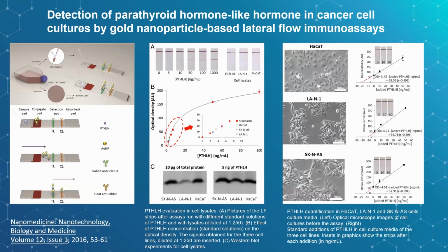And we offer these devices based on gold nanoparticles and with special receptors for the detection of this hormone. The idea was to use this device for testing some drugs that colleagues were developing, and we wanted to have a very simple alternative. As you can see here, it had a very nice variation with the concentration of this hormone in the optical density, and of course, comparing these results with conventional techniques, we could work nicely in different culture media, doing some testing that showed a nice correlation that improves sensitivity.